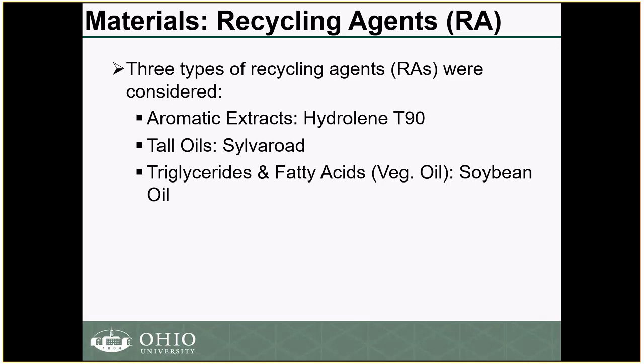Based on the literature, we found that a lot of researchers suggested that when you go beyond 30% RAP, you might need to use a recycling agent. Based on that literature review, we identified 3 different types. Aromatic extracts, and an example that we used is Hydrolene T90, though there are other aromatic extracts available. Tall oil, for which we used Sylvaroad. And then the triglycerides and fatty acids, for which we used vegetable oil, which is soybean, the generic soybean oil being used in the market.